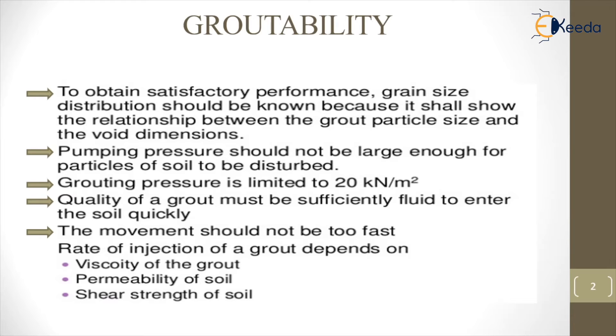Groutability is the ability of a grout mix to perform well. To obtain satisfactory performance, the grain size of the grout mix plays an important role. The grains of the grout mix should be able to pass through the voids of the soil particles. The pumping pressure of this grout mix should not be large enough to disturb the soil, so the pressure is limited to 20 kN per meter square.